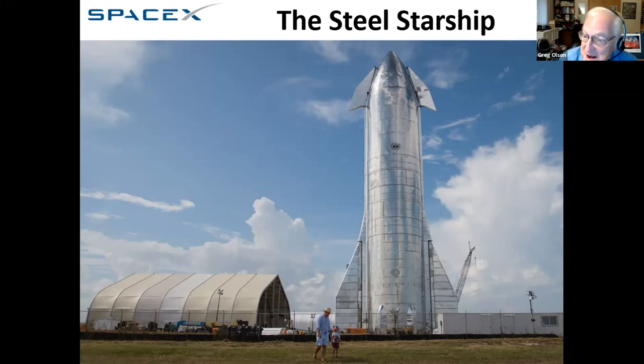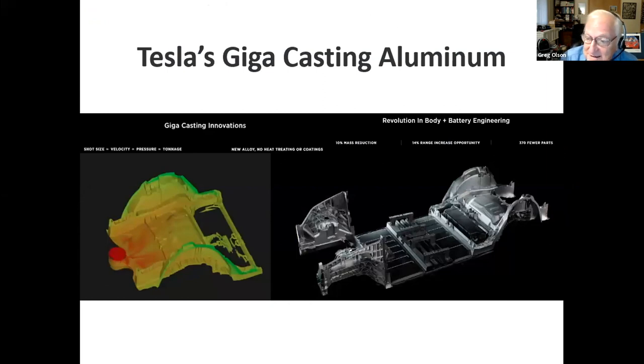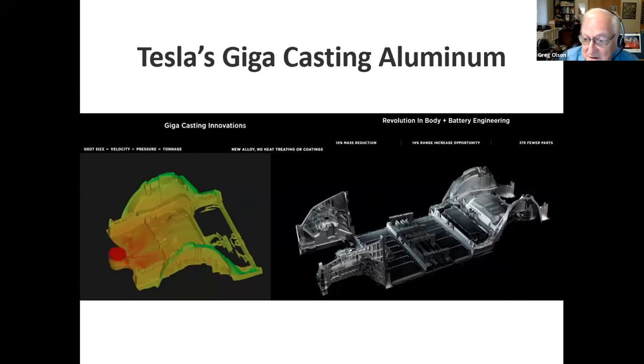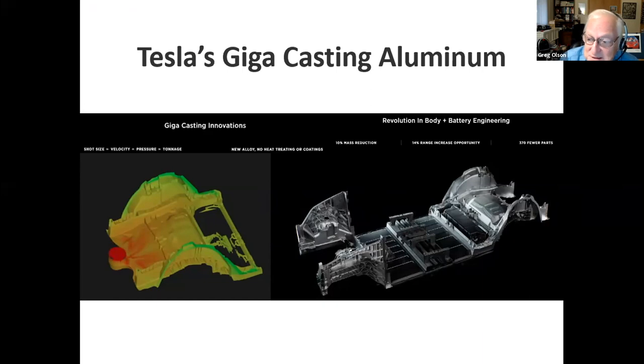I'm sure Harry is very pleased with that example. Over at Tesla, it's been a really exciting innovation in automotive structure technology — possibly one of the greatest breakthroughs — in the concept of gigacasting. Musk's vision was to scale up die casting so that he could make the aluminum structures needed for the lightweighting required to get enough range out of a fully electric vehicle, making the aluminum structure from just two parts. This was a colossal achievement, and the very first step had to be the design of a very novel alloy — a CALPHAD-based design using eutectic phase fractions optimization to achieve the desired strength and ductility in the as-cast state.